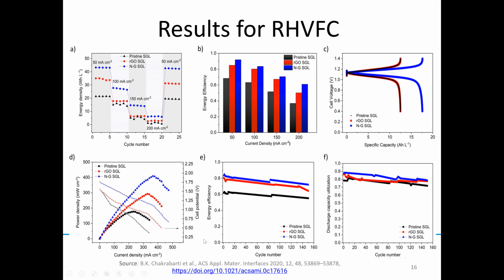Then we did cycling for over 150 cycles and compared key performance indicators, i.e. the energy efficiencies, and how that varied for three different electrodes: the standard carbon paper, reduced graphene oxide modified carbon paper, and nitrogen doped graphene carbon paper. And we found that the nitrogen doped graphene paper is performing better in the hydrogen vanadium system.